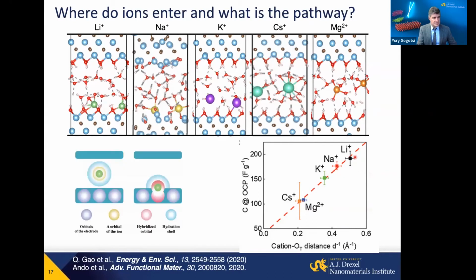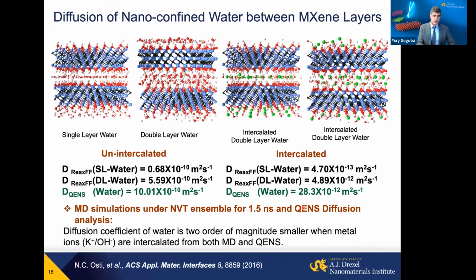surface. Naturally, what it means, ions that come close to surfaces, hybridizing orbitals with oxygens and transition metal, they will lead to stronger polarization, transfer more charge, and it means providing higher capacitance compared to some other ions, more charge storage. We also need to understand dynamics, because transport in a bulk solution is very different compared to transport in confinement. And we found that basically dynamics, diffusion coefficients of water molecules in presence of ions in confinement can be by 2-3 orders of magnitude lower compared to bulk materials.